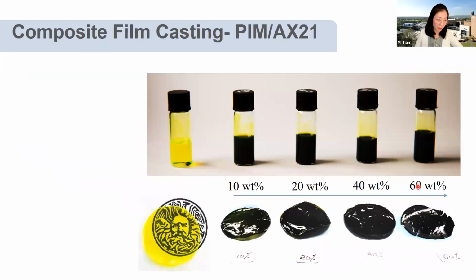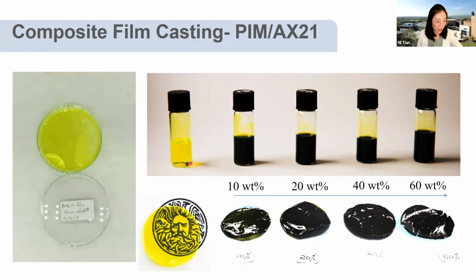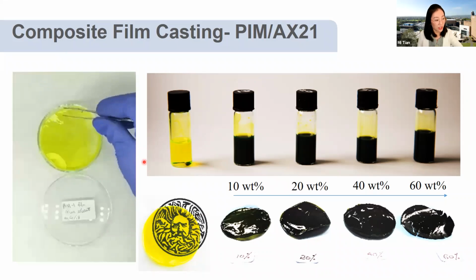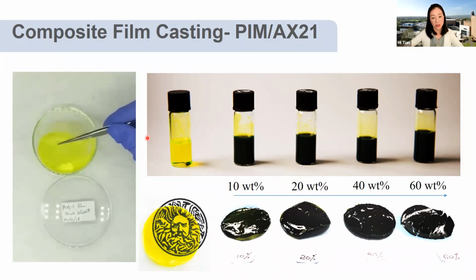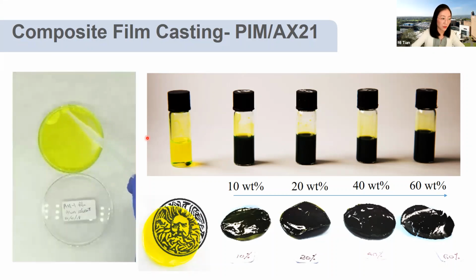So we mixed the PIM1 polymer and porous fillers together and dissolved them into a solvent at different concentrations. And then we pour them into a container, a petri dish, and let them dry. Then we just drop a few drops of water on the dried membrane. The water will automatically go underneath the membrane and lift it up. So that's how we cast the film.